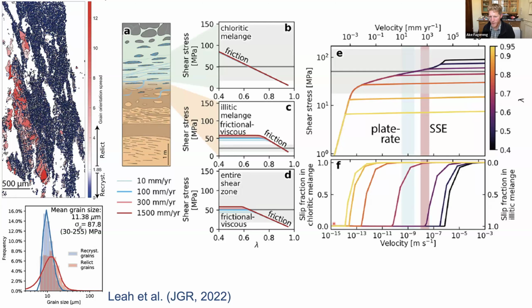You have pressure solution accommodating the deformation at lower rates when fluid pressures are relatively low, so when stresses are a bit higher. And then if you locally increase fluid pressure and decrease effective stress, you have a switch in which part of the melange takes up the deformation, and a potential change in velocity.